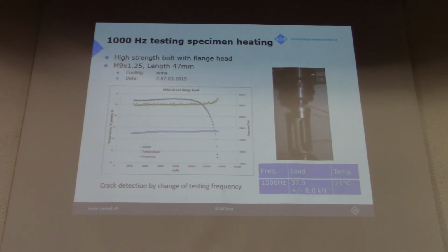There are other materials where the heating is not an issue. Here is an example of a high-strength bolt where we could test at quite high load, where the life is below 200,000 load cycles. And here we see the green plot, again, the temperature, and the heating up is negligible. So it can also be interesting for some components and parts where we can reduce the testing time dramatically.